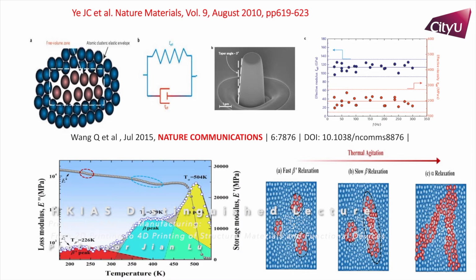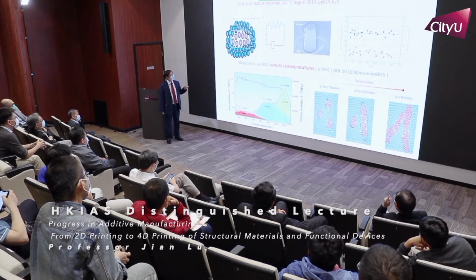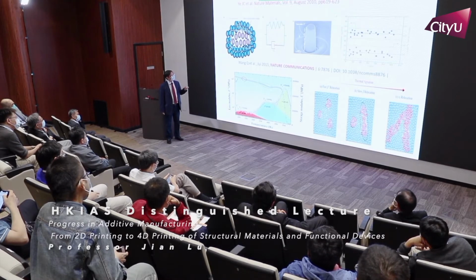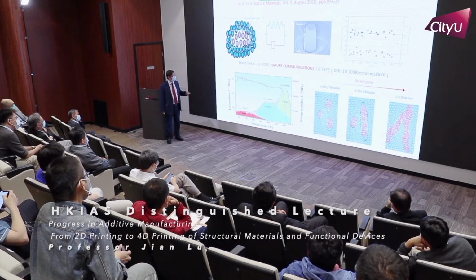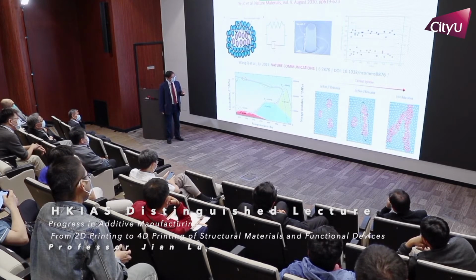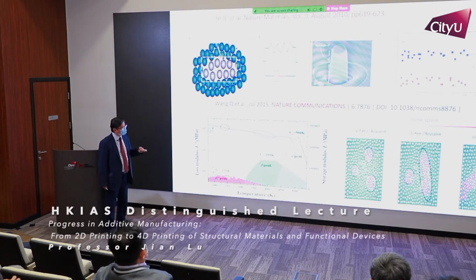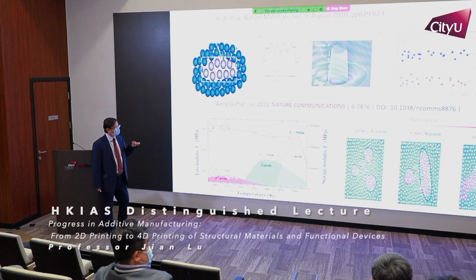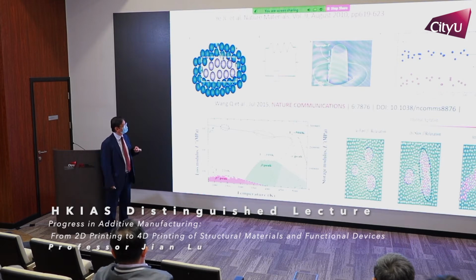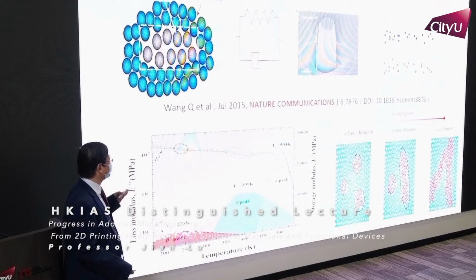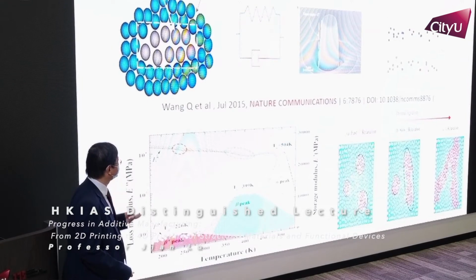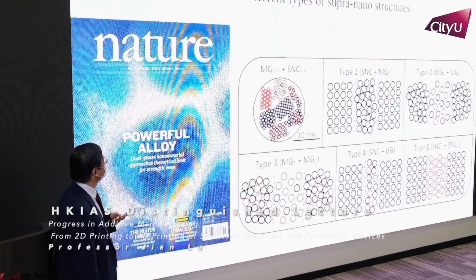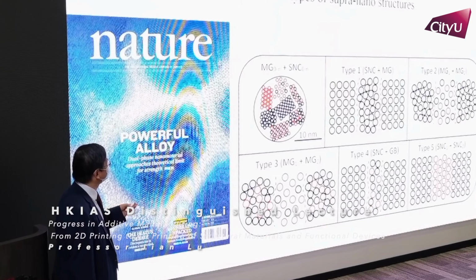Then we tried to better understand the material with their heterogeneity. So we developed a dynamic micropillar test and also a fast beta relaxation to better understand the relationship between the heterogeneity at atomic level with mechanical property, especially the, say, shear band initiation. Okay? Then it's quite difficult, and then we switch to a new type of material, which are supra-nano structures.